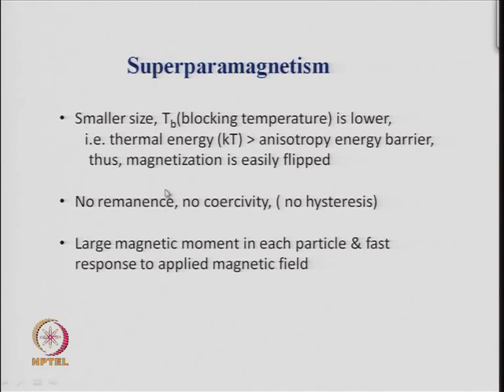And this is due to the fact that the thermal energy is much larger than the anisotropic energy barrier, that is U we discussed, and the smaller the size of the particle, this U will become even smaller, and thus magnetization will be easily flipped. So, the blocking temperature gets lowered with the size of the particle.